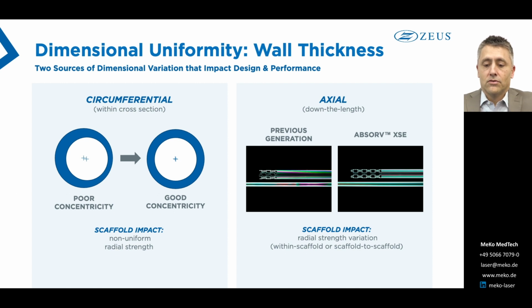We typically refer to within cross-section variation as concentricity. So if you think about the inner and outer diameter of a tube, think about them as being two circles. It's really that center point of those two circles being misaligned. And what happens there is you end up with a thin wall on one side of the tube. And this can cause a BRS to have a non-uniform radial strength in that circumferential direction.